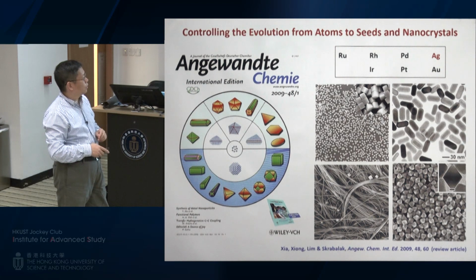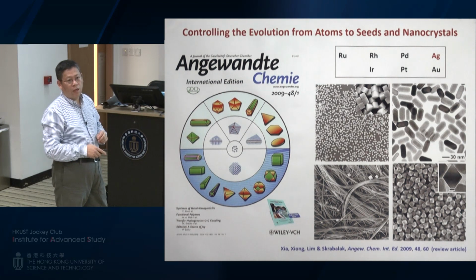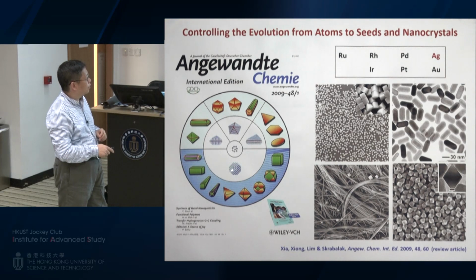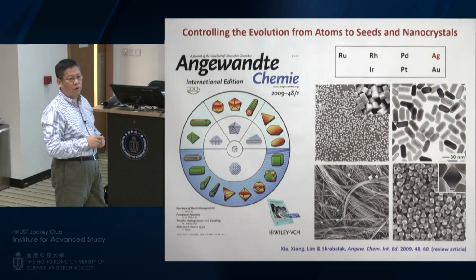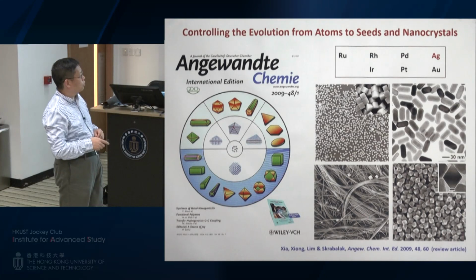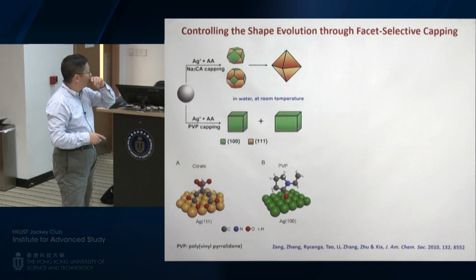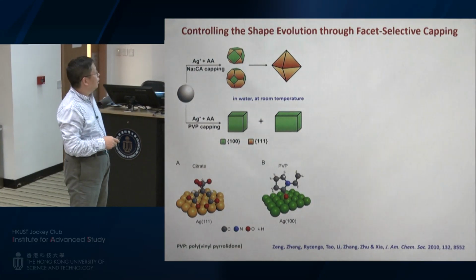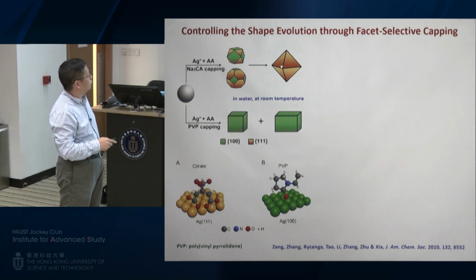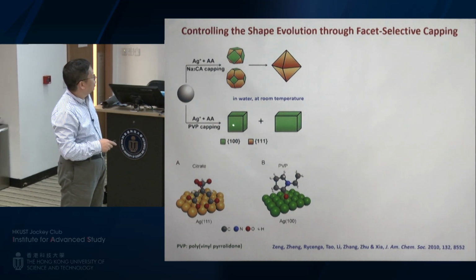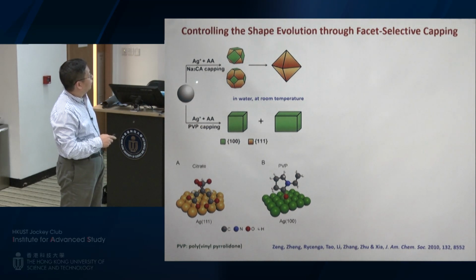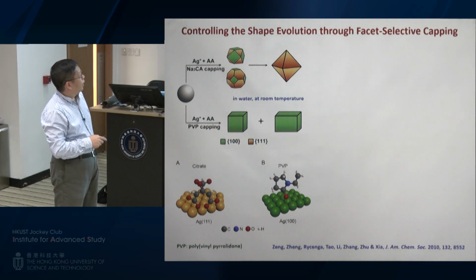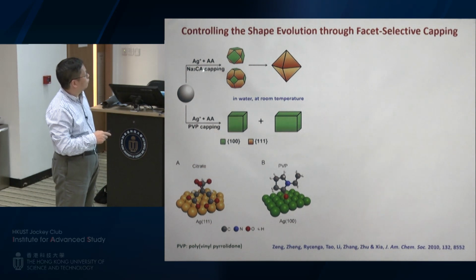So that's why people start to look at seeded growth. In one step, we just make the seed, and then we have another step of growth, so you can have very good control in terms of shape. So let me show you just one example. In this case, we are making silver octahedra and cubes by starting with a single crystal seed. We can make it. And then for growth, you just add more silver nitrate and ascorbic acid to serve as reducing agent. And now you can play the trick of capping agent.